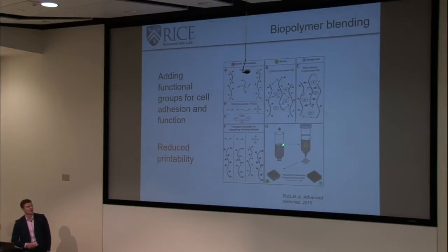On the other hand, we've successfully and honestly pretty easily incorporated both gelatin and alginate into the same printer head, and then your printability actually increases from going with just gelatin or alginate alone, because you have a couple different cross-linking methodologies you can use, and you also don't have to incorporate a high concentration of either polymer.